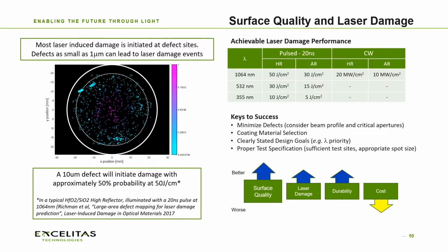We've got to understand the apertures so that we're not over-specifying, trying to specify minimal defects over very large apertures. It gets cost prohibitive very quickly. So we need to understand very clearly what the aperture sizes are and the fluences at different places within the aperture size. And of course, properly specifying the test is one of the most challenging things that we do. But making sure that we're clear about the spot size and how many sites are going to be tested and what we actually know based on the result of that test is going to be a key consideration.